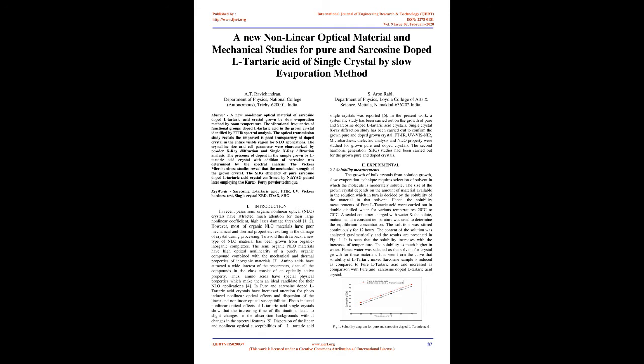2. Experimental. 2.1 Solubility measurements. The growth of bulk crystals from solution growth. The slow evaporation technique requires selection of a solvent in which the molecule is moderately soluble. The size of the grown crystal depends on the amount of material available in the solution, which in turn is decided by the solubility of the material in that solvent. Hence the solubility measurements of pure L-Tartaric acid were carried out in double distilled water for various temperatures from 20 degrees Celsius to 70 degrees Celsius.